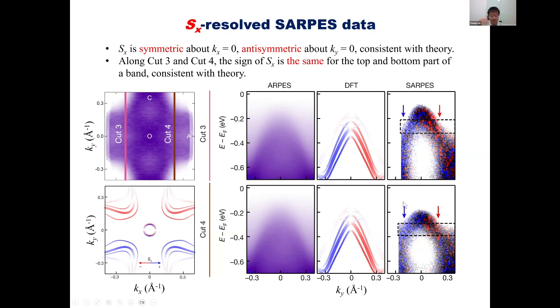It looks a little bit noisy in all of this data. That's because the efficiency of the spin detection is very low. Each graph here takes about 14 hours, and the sample stays alive in the vacuum chamber for about 24 hours. So for each sample we can take only one or two of these cuts, and that's it. This is not a very easy measurement to do.